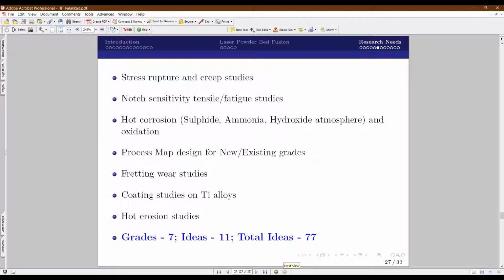So it is important to study the notch effects, which will help you to understand the complex shapes effects, or geometry effects, on the properties. So create a notch with a different stress concentration and study its behavior in tensile or static mode and the fatigue or dynamic modes. Gather the data, which is very, very important because titanium alloys are notch sensitive in nature.